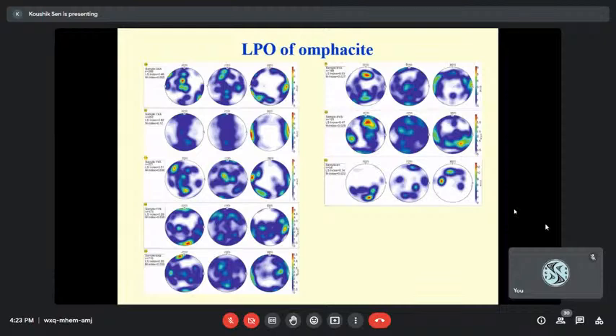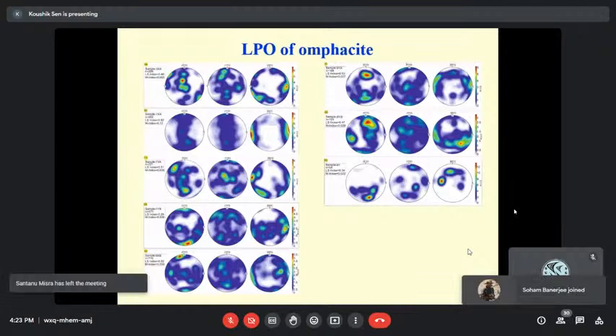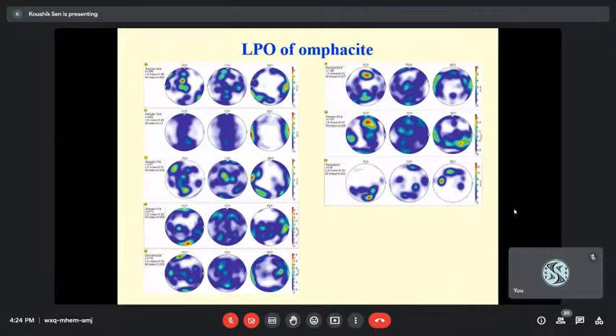And apart from this, there are samples like the ones to the bottom of your left, where you can see that instead of a point distribution, it is more like a girdle distribution, which you can infer is more like a mixed fabric, that is LS or SL type, mostly for type 2. But in some cases, say for example the last one, which is among the most retrograded samples, and a few others, the LPO doesn't really make any sense.